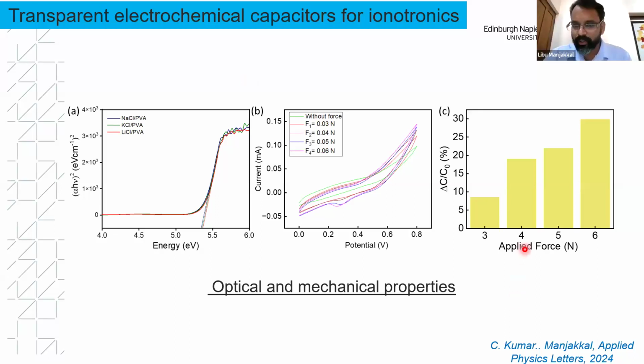Please continue. Currently, we found some issues with this work. When we have a gel electrolyte with the transparent electrochemical capacitors, there is leakage of the electrolyte during bending, so we need very strong packaging. So we are now trying to overcome this issue with solid electrolyte-based ionic components, and we got pretty good results. I'm not presenting that result here. One piece of good news is that this work was shortlisted as one of the best journal works by Applied Physics Letters last month, and we got very good appreciation for this work.